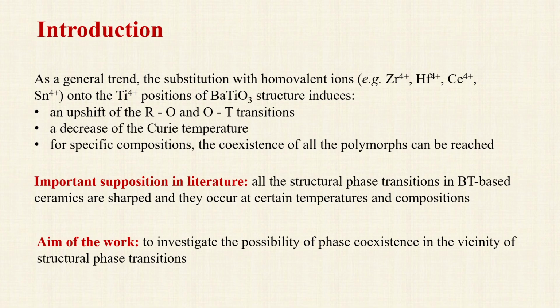However, many of these aspects accepted in literature are derived from the studies of single crystals. Ceramic materials are more complex than single crystals, with complex domain structures and random rotations of the grains and orientations of the polarizations. Therefore, we propose to check if structural phase transitions are sharp and occur indeed at a certain temperature, or if it is more realistic to consider that phase transitions are produced in a range of temperatures for which at least two phases might coexist.